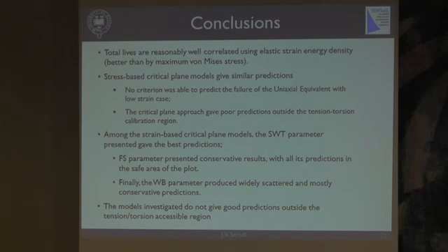So that's about it really. Elastic strain energy is probably actually the best of what we've got, but it's not terribly intellectually satisfying, I don't think. The stress-based critical plane models give similar predictions, but none of them was able to predict the fact that this was the longest life.